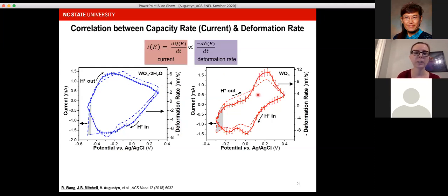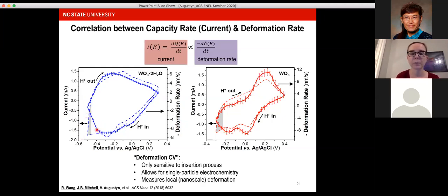of the materials. The places where you don't see a good match at these potential extremes is due to the onset of the hydrogen evolution reaction in the electrochemical current, which is not resulting in any volume change of our insertion electrode, and so we just don't measure anything with the AFM tip. So it's highly sensitive to the insertion process.